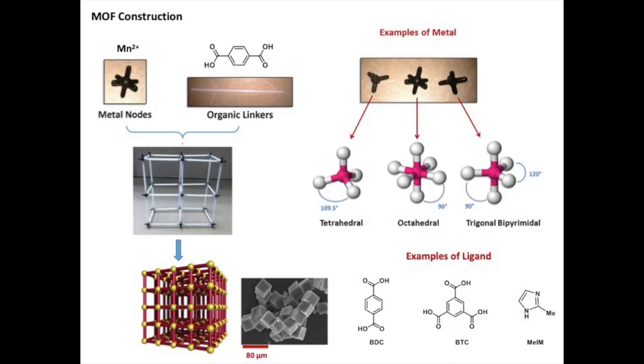It's also interesting that these materials are modular, which means we can use different metal centers with different coordination spheres. For example, we can use a tetrahedral based metal with the coordination sphere, as you can see, it would lead to a tetrahedral structure, or octahedral, like here we have the octahedral structure, as well as the trigonal bipyramidal, and actually there are more metal coordination spheres.